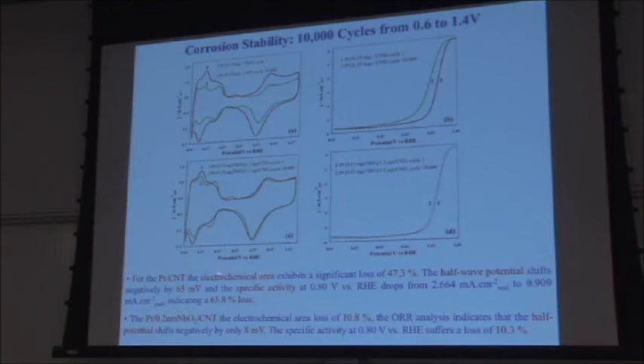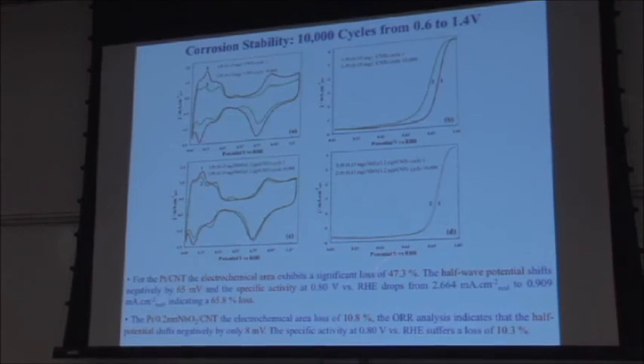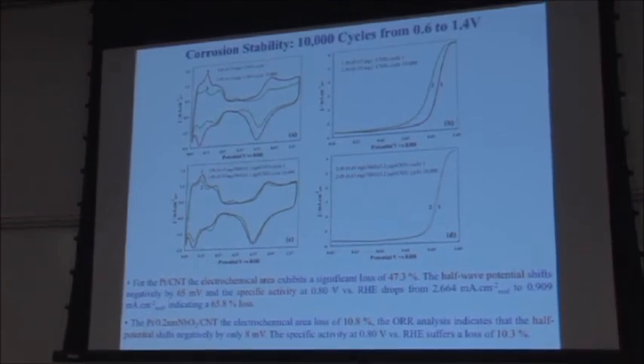So platinum on carbon nanotubes lost 47%. So it's still a little bit better than commercial systems, but you're in the same range in terms of loss. Half-wave potential shifts 65 millivolts, specific activity loss 66%. If you introduce a 0.2 nanometer layer of niobium oxide, you have a loss of 10% in electrochemical area, the half-wave potential shifts 8 millivolts, and specific activity only 10% loss. So to our knowledge, this was really, the referees kind of agreed with us, probably the most corrosion-resistant electrode architecture for this class of nanomaterials reported in literature.